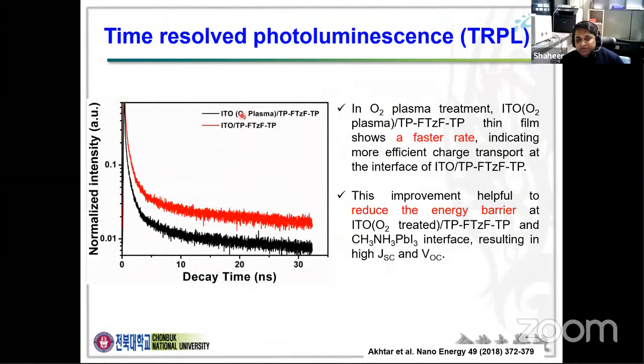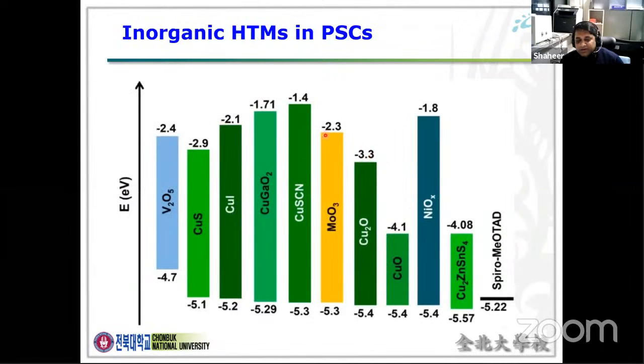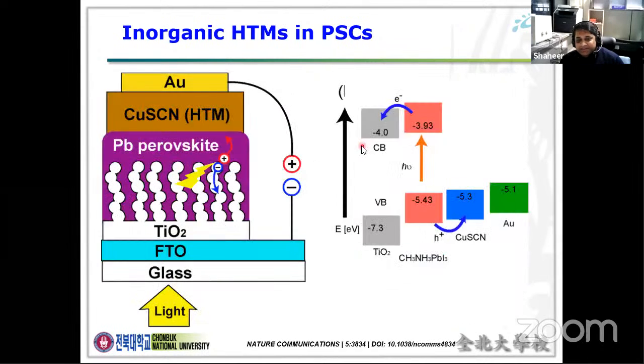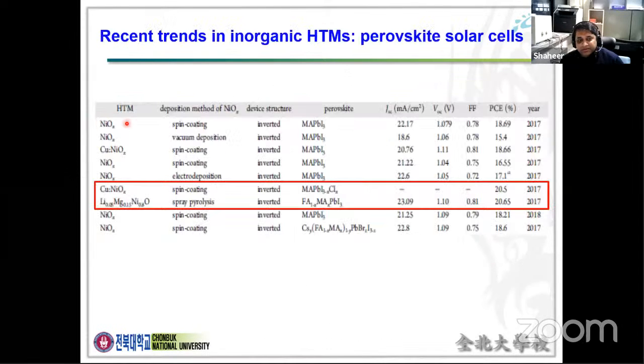And the main reason is that we also performed an oxygen plasma treatment, which significantly improves the electron transfer rate, and the decay time is decreased, so that increases the fill factor and VOC of the perovskite solar cell. We also have some inorganic work, so I'm just skipping this one. In our laboratory, we are focusing on nickel oxide based HTM materials.